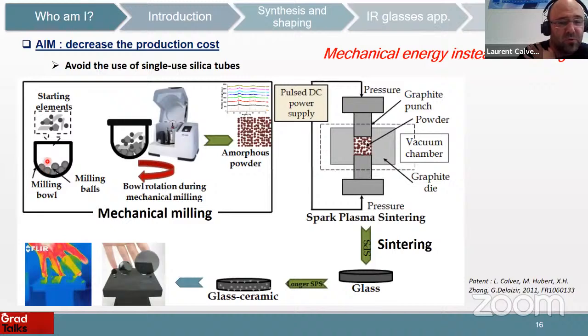So what we have done is just to put all the starting elements, germanium, arsenic, selenium, etc., in a jar with milling balls, and we let it turn for several hours, around tens of hours. And at the end, you also get a reaction during the mechanical stress. You have a reaction between all the raw elements, and you have at the end an amorphous powder, which is exactly the same composition as the glass.